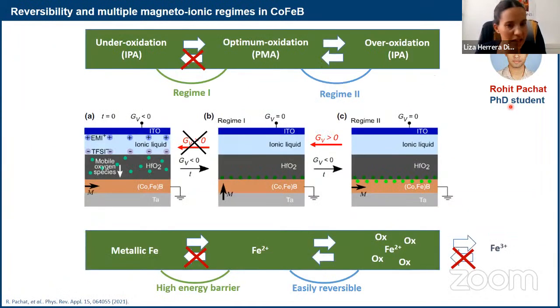So our interpretation of this is that when we go from the under-oxidized state to the optimally oxidized state, we start with metallic cobalt and iron, so this is pretty easy to oxidize. Any oxygen that comes in contact will bind to, in this case, I make the example with iron because it's an iron-rich film. It will bind to the iron, and the iron will transition from metallic iron to iron 2+, which is something we saw before in the XPS. So this has a relatively high energy barrier. This is a proper change in the oxidation state of the iron.